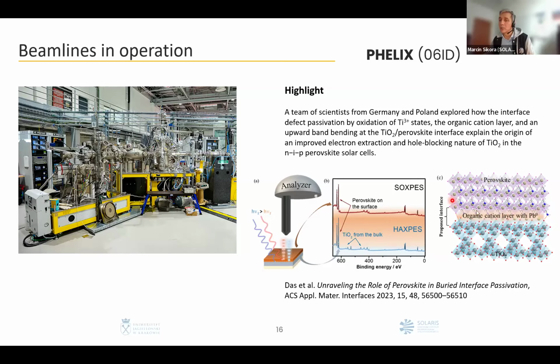The example that I'm showing here is a perovskite film that was deposited on titanium dioxide. So scientists here were able to observe not only the electronic structure and composition of the perovskite film with photoelectron spectroscopy, but also they were able to reach the titanium dioxide substrate, and especially the interface that is formed between perovskite and titanium dioxide.